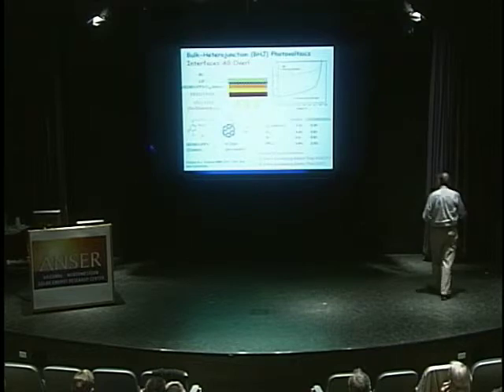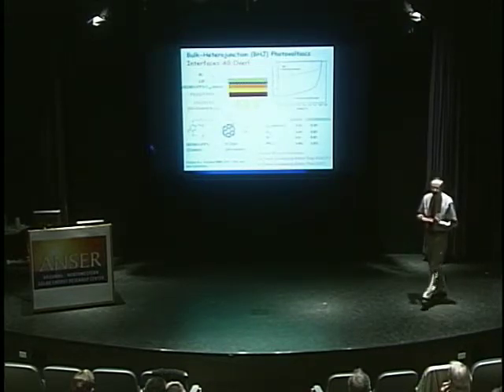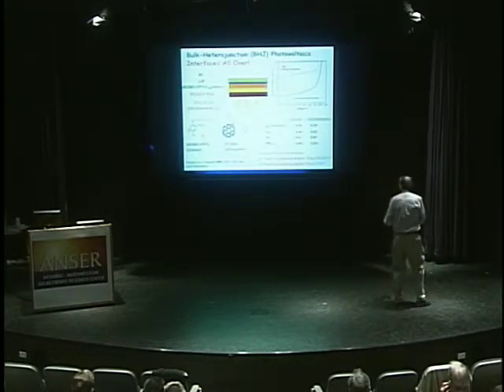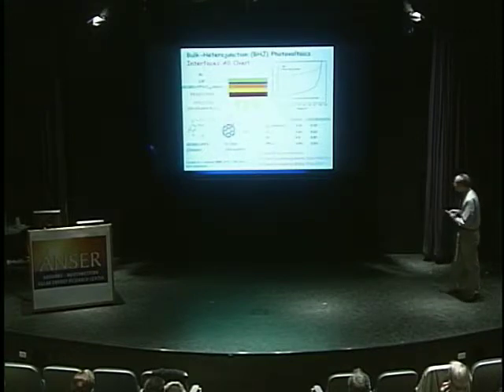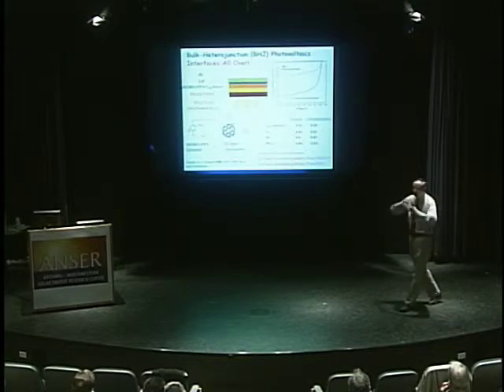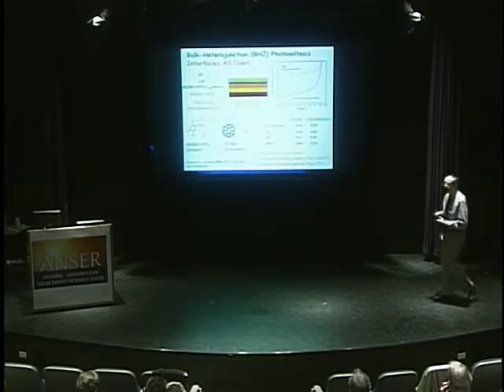The subtleties of the microstructure are beautifully illustrated. Here are results for 2 different cells, and all that has been changed is the solvent that the film is cast from, toluene to chlorobenzene, and you can see the efficiency goes up almost by a factor of 3. It has to do with the microstructure, with how these materials phase separate. And so the kinds of questions to ask are, just how important are all these interfaces? Is there something better than PEDOT, and is there something better than ITO? And that's basically what I want to talk about this afternoon.